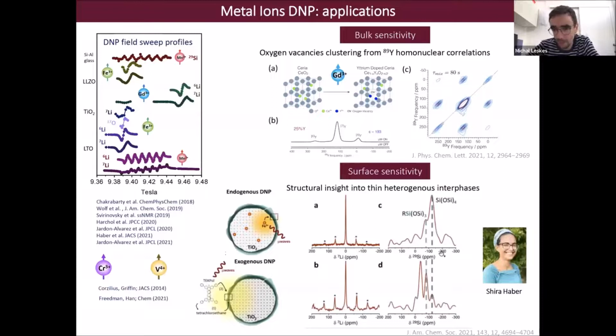And another example, Shira in our group worked on characterizing coatings of different particles. So the idea here is that adding a coating on a particle can be very important for lithium-ion batteries. And in this study, she combined the endogenous metal ion DNP approach with the exogenous approach. And by doing measurements with these two different approaches, she was able to characterize the coating from the inside out and from the outside in. This way, we were able to obtain chemical information or information about the chemistry of these coatings. And not only that, we were also able to get compositional gradients within this coating.